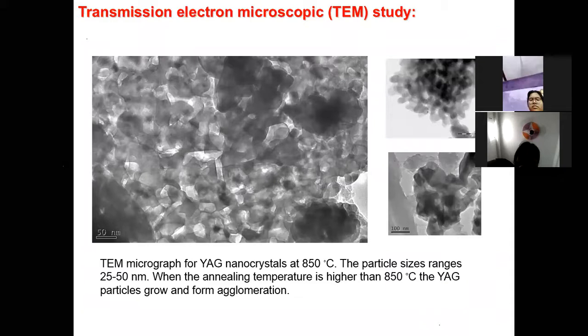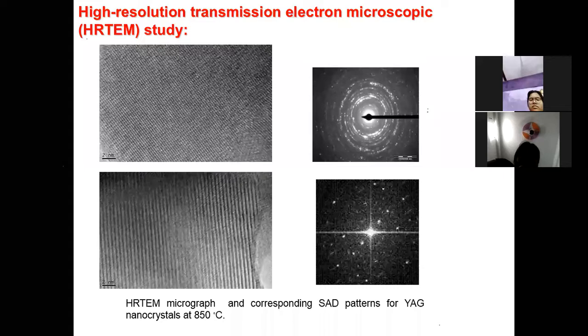If you go to a higher temperature, the size will increase, but again the size is well below 100 nanometers, so it can be used. This is the work done by Nanda. Most of the work is done by Nanda. High resolution again shows how these structures are, and this corresponds to selected area diffraction. If you see the corresponding selected area diffraction, it tells that it is beautifully structured, and this is the desired structure we were trying to make.